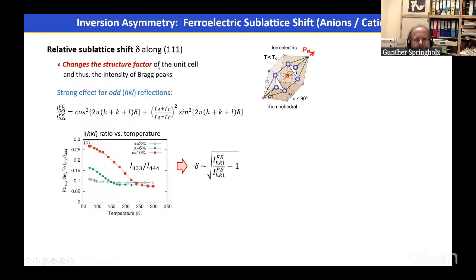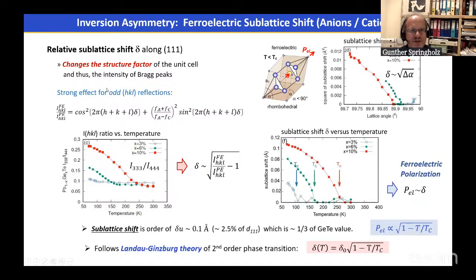What is important, this rhombohedral distortion alone does not tell anything about the ferroelectric properties of the material, because ferroelectricity comes not from the distortion of the cubic lattice, but rather from the lateral shift of the sublattice, indicated here by this red arrow. So meaning that in the ferroelectric phase, the anion and cation sublattice have to be slightly shifted with respect to each other to produce the ferroelectric polarization, that is the important property of a ferroelectric material.